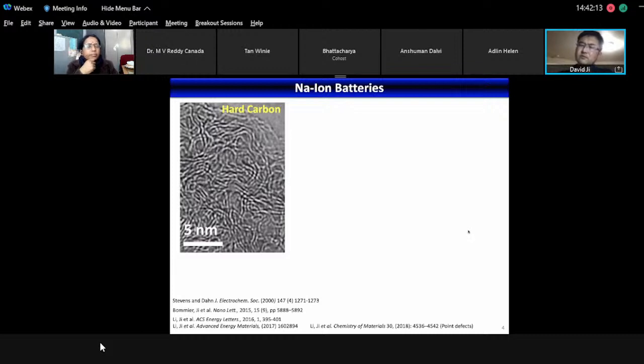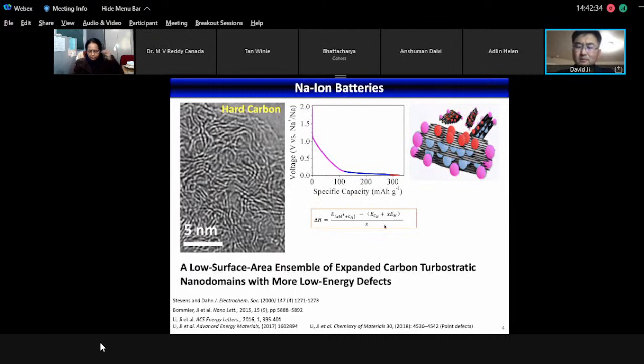In 2012, when I started my group, my first project was to study an anode for sodium-ion batteries. That was my interest for a few years. I want to condense what I have learned on hard carbon over the years. I don't have time to explain how I arrived at the conclusion. The design principle of hard carbon, in one sentence, is a low surface area material to minimize the side reactions on the surface between the electrolyte and the electrode. You want an expanded carbon turbostratic structure so that you can promote the sodium ion storage for the plateau. You want more benign, low energy defects of the carbon so that you can promote the slope of the profile for the storage of sodium ions.